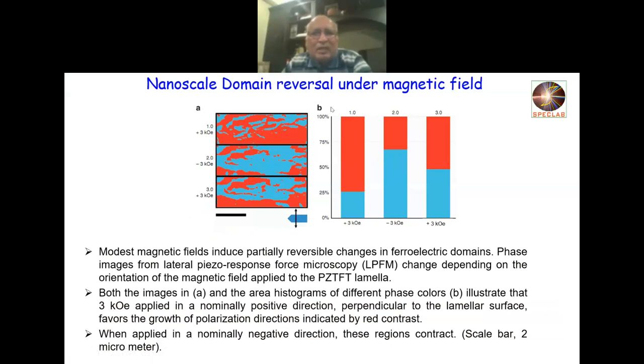We did later on nanoscale studies in this one. In this case, by microscopy, they have two kinds of domains, the red and the blue, and see how they change with the field. There is a 3 kilo field, a very small field being applied, to see how the domains change. You can see that there is a switch over of the domains. We have plotted here all the domains, the one kind and then the other kind. And you can see that as the field changes from 3 kilo positive to negative, there is a big change in the total domains. So all these things have proved that there is indeed magnetoelectric coupling present in this material.